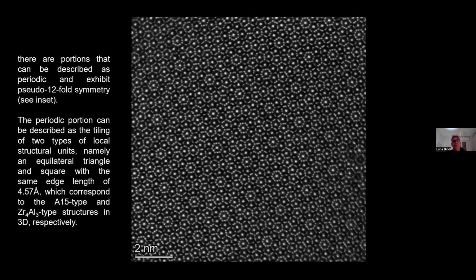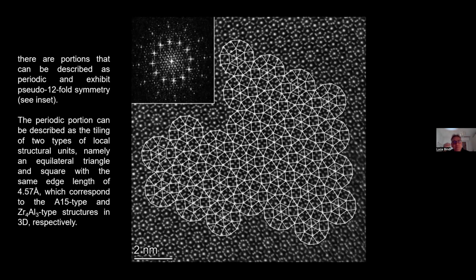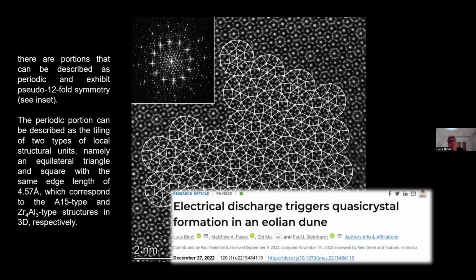And another interesting point, if you look at the larger high-resolution image, you can see that this kind of dodecagonal quasi-crystal in the fulgurites coexists with an approximant. When I say approximant, I mean a periodic object which shows similarity to the quasi-crystal. So it shows some structural features typical of quasi-crystals, but it can still be described as periodic. And indeed, if you look carefully, you can decorate most of the grain with a periodic approximant, but you can see that on the top and on the bottom, you have the perfect quasi-crystal. So exactly as it happens in the synthetic dodecagonal quasi-crystals. And again, if you want to get more information, you can find everything in this paper published again in the Proceedings of the National Academy of Science.